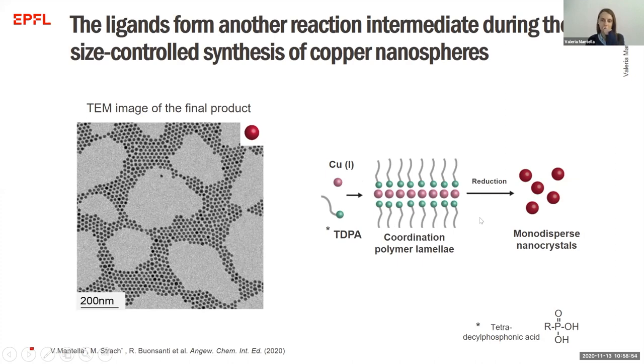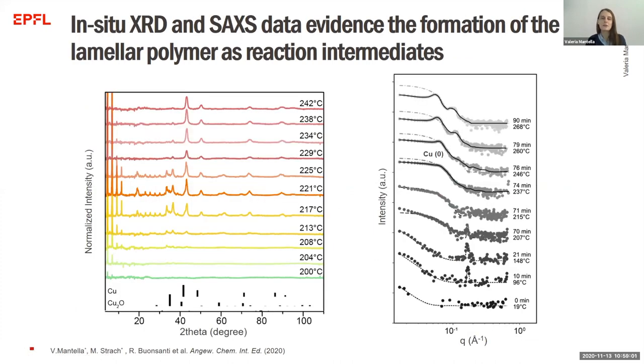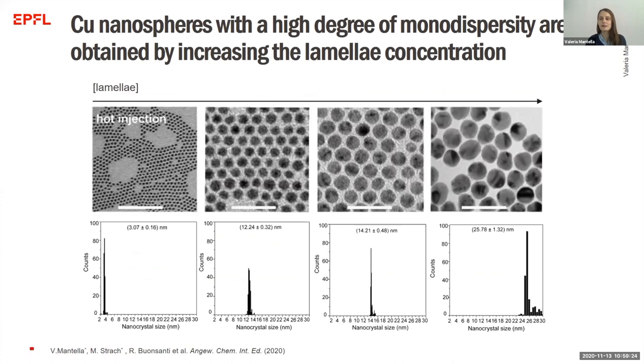And once again, we could deduce this reaction mechanism by using in situ X-ray spectroscopy. Here, for example, I'm showing you in situ XRD patterns and the SAXS spectra collected at different temperatures. In both of them, we could follow the formation of the lamella and then its evolution into copper particles. And so once we have identified this reaction intermediate, then we modified its concentration in order to access bigger sized copper nanocrystals with a higher degree of monodispersity, as was then confirmed by TEM analysis.